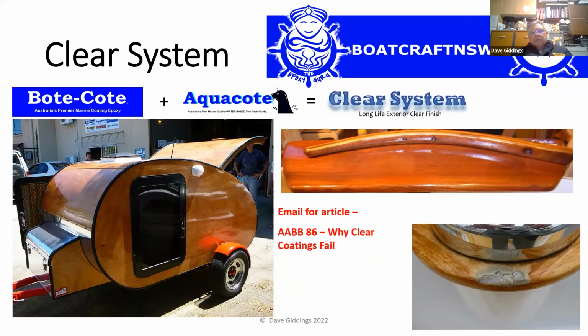How you get a good clear finish to last any length of time out in full sun is you seal the timber right around with boat coat, and that includes bolt holes, screw holes, any penetration into it has got to be sealed. Then, because the epoxy can't handle the UV, you put the clear acrylic over it, anywhere from two to four to five coats. The more coats of the polyurethane you put on, the longer it's going to last. What that does is keep the sun away from the boat coat.